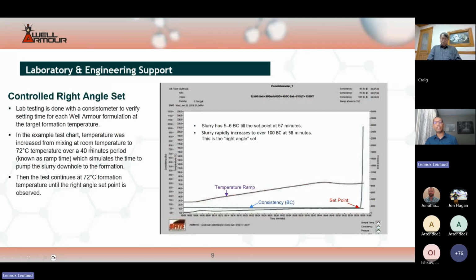So lab testing in most cases is always done on the Well Armour slurry prior to a job. The test primarily done is a set time test, also known as a thickening time test when done for a cement slurry, because the equipment used to perform the set time testing is a standard consistometer that's typically used to perform thickening time testing for a cement slurry.